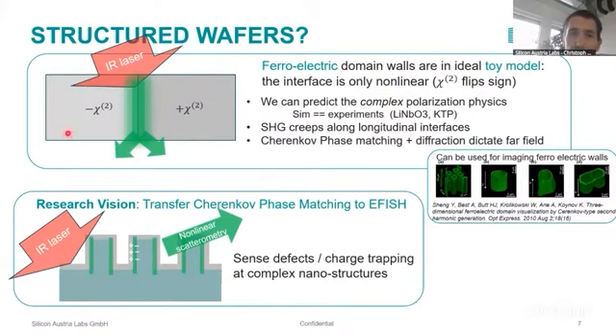The experimental data for this toy model typically comes from lithium niobate and KTP, periodically poled, which has a different use case for quasi-phase matching, basically. But we use this in the configuration where we propagate along the interface, basically. So we learned a lot of things from these toy models and set up our basically numerical simulation code base, and then want to transfer this to real-world samples away from the toy model. This Cherenkov phase matching that I explained here can also directly be used if you want to image ferroelectric domain walls. So this has been demonstrated, but this is also not by us, in this very interesting paper here, where you can see 3D images of these domains, basically.